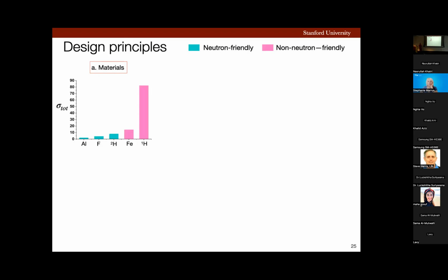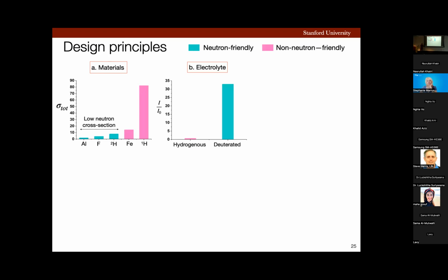Now, let's look at some of the actual battery materials. Here you can see hydrogen has a significantly high value for sigma total, and so does iron. And hydrogen is present everywhere in the battery, in organic electrolytes and in the hydrogenous battery separator. So in order to make a battery neutron friendly, we have to replace hydrogen with deuterium or fluorine, and iron with aluminum-based materials. Thus, the first modification I made in my battery was to replace a hydrogenous battery electrolyte with a deuterated electrolyte. And you can see here, this increased the transmission significantly through the battery. Next, I replaced polypropylene, which has a significant hydrogen content, with a fluorinated polymer. And again, we have a significantly higher neutron transmission.